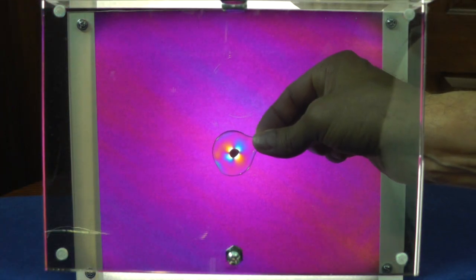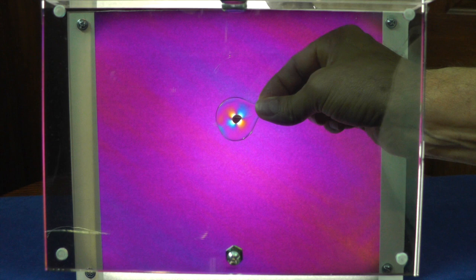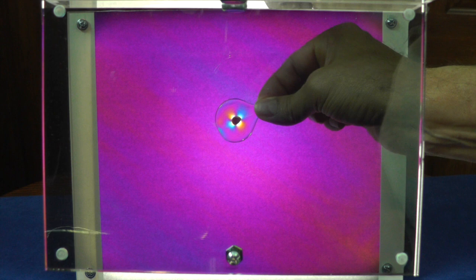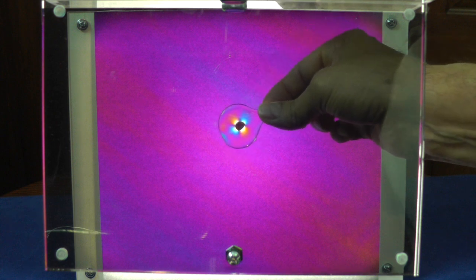You can see with this sample, this is 104 clear and 96 color, and you can see that because of the difference in expansions, how severe the strain is. You see how sharp the edges of the color are and how bright the colors are. The transition between the blue and the yellow is very sharp, so this denotes a heavy strain. Probably if this glass was a lot thicker, the amount of color would crack the glass.